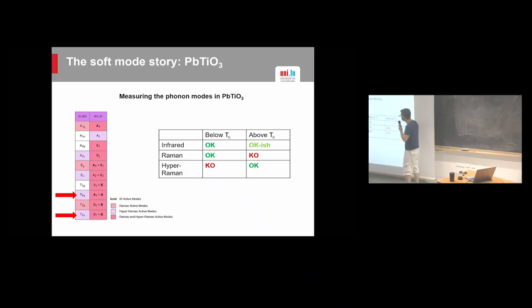If you go above TC, infrared, I say okay-ish, in the sense that symmetry-wise it's allowed, but we're talking about quite high temperatures already, where modes tend to be smeared out by temperature effects, so you can measure them, but it may not be the best technique if you want to have a nice accuracy. Raman doesn't work. The modes are not active in Raman, so that's it. This is for symmetry reasons, but this is where hyper-Raman comes into play and can be a very nice complement.